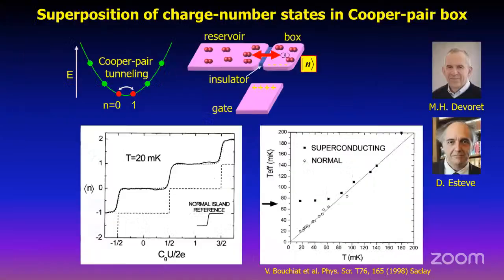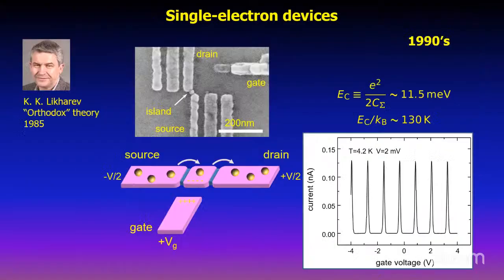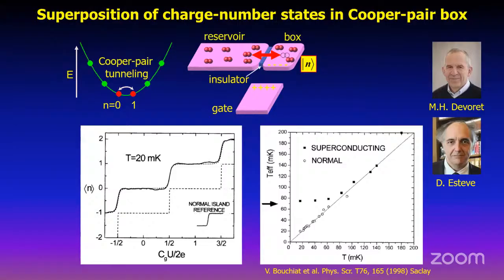Okay, this was in the normal state, with no superconductivity, but when aluminum electrodes become superconducting below 1 Kelvin, we started to see this effect of single Cooper pair tunneling across the Josephson junction. And here, the competition between the Josephson effect, which tries to delocalize Cooper pairs, and the charging effect, which tries to localize Cooper pairs, gives an interesting situation where we see the quantum fluctuation of the charge and the phase compete.